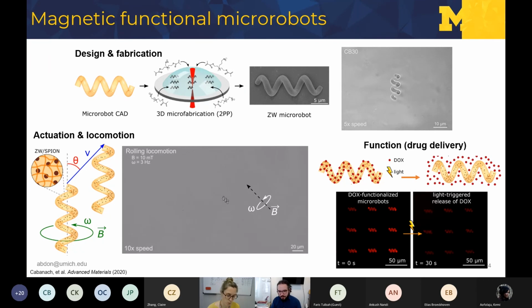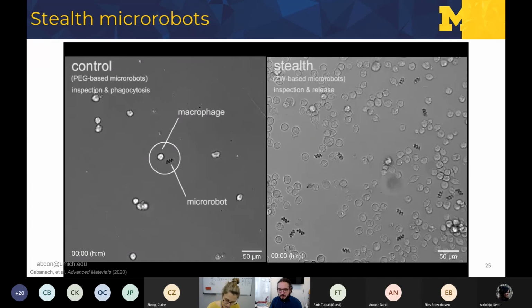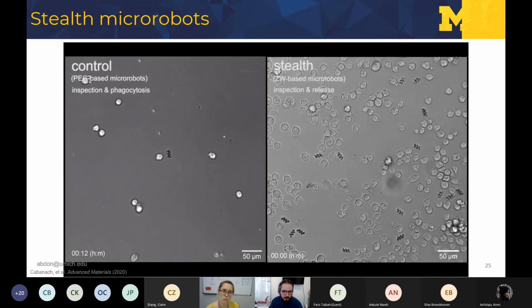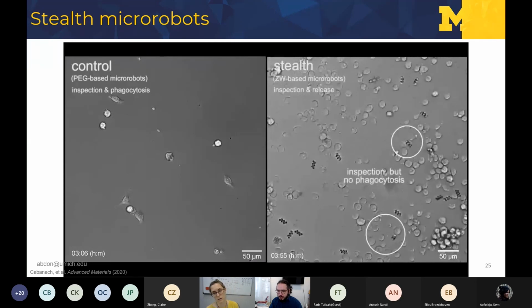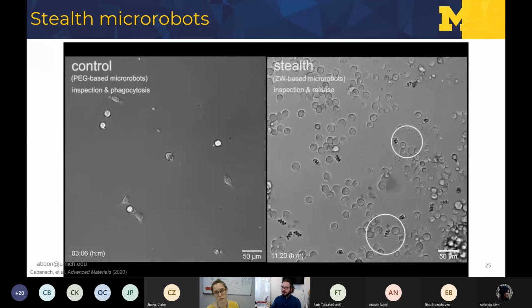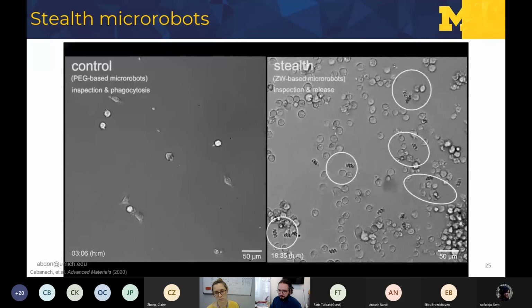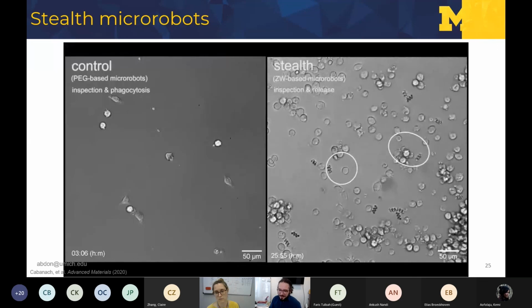But what we were more interested in is seeing how these zwitterionic polymers behave when in contact with immune cells, right? So we co-cultured them with macrophages and with splenocytes, and you will see here there's a big difference between the PEG-based microrobots here on the left, which is the current gold standard for anti-biofouling materials, and our zwitterionic microrobots here on the right. So you'll see that as soon as the macrophages come in contact with, I hope the video can play well over Teams, but you can see that as soon as they come in contact with the microrobot, they're captured immediately. While with the zwitterionic microrobots, you can see that they don't, right? You can see that the macrophages are inspecting them. They know that something is there, but they're really not triggered and not attacked by the macrophages.